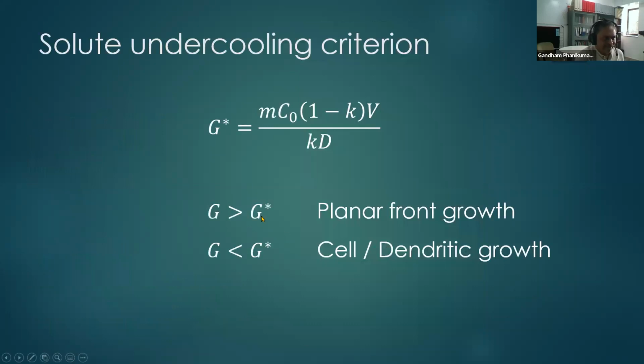So this is a criterion I was talking about, the solute undercooling criterion or constitutional supercooling criterion, which tells you when this breakage happens. In the case of additive manufacturing, the velocity is known and the partition coefficient of the material is known. The liquidus slope is known, concentration of the liquid is known, and therefore you can actually predict what conditions will give you the cellular formation.